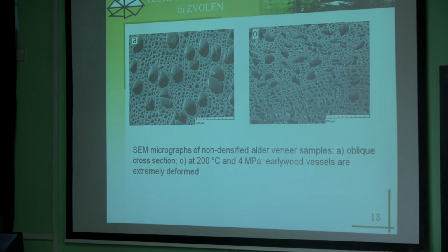Here are some scanning electron micrographs, and we can see the influence of the pressure. These pictures are taken from alder veneer, and here is the picture of regular wood, and here is the picture of the same sample after pressing at the pressure 4 megapascals at temperature 200 centigrades. And you can see the difference between openings of wood, between the shape and dimensions of fibers and pores and capillars of wood.